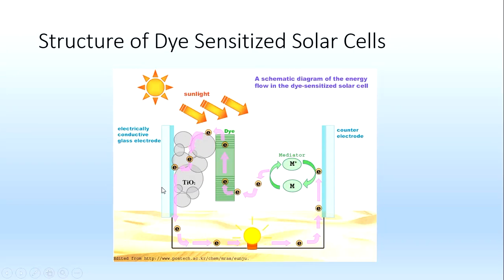And so what I did in my experiment is that I used zinc oxide, one with nanowires and one with a nanophore structure. The nanowire structure was interesting because even though it had fewer grain boundaries, it actually ended up doing worse than titanium dioxide. So what's good about titanium dioxide? Well, it has a high surface area, so it's able to hold a lot of electrons within the dye. But with the nanowires, it didn't have a lot of surface area, so there's not a lot of inherent electrons in the dye as a result.